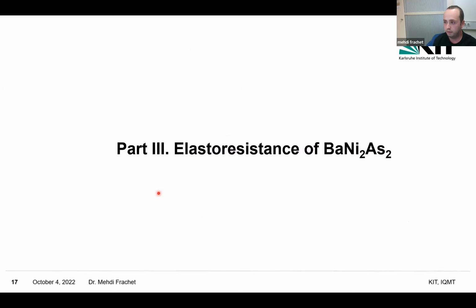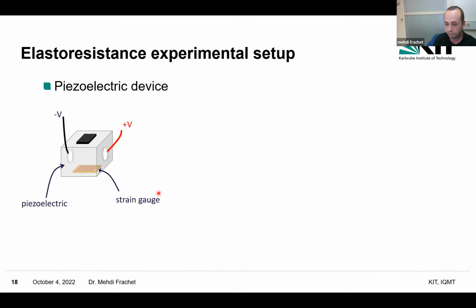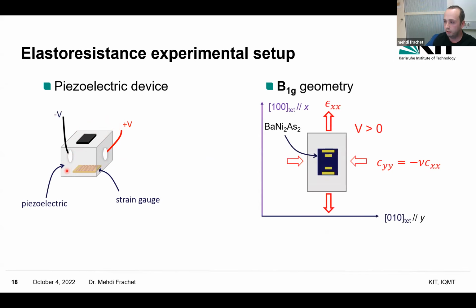Okay, so let's first talk about the elastoresistance of this undoped barium nickel 2 arsenic 2. So we have used the same setup as was used already 10 years ago by Jan Fischer. You see a simple piezoelectric device. The sample is glued on the top surface. There is a strain gauge on the back side, and it allows us to estimate the strain that we transmit to the sample. Okay. So I will show you data in this B1g geometry. That means that the a-axis, the tetragonal a-axis of the sample, is aligned with the pulling direction of the piezo.